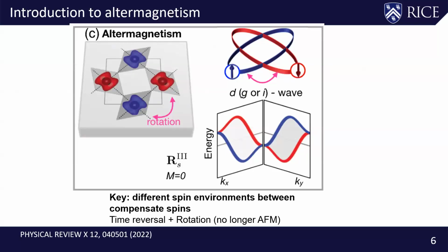The recent claim of an altermagnet, in this context, is a system that is still strictly a simple collinear antiferromagnet, except that the translational symmetry is obeyed, but you need to rotate your local environment by 90 degrees in order to repeat itself. The band structure calculation in such a situation suggests that you would have spin up and spin down bands split in some portion of the reciprocal space. That is in terms of electronic bands. If you simply think in terms of spin wave bands, naively, if the system is completely collinear, it should be identical to the case of a simple collinear antiferromagnet, where the left rotating and right rotating spin waves should be completely degenerate.